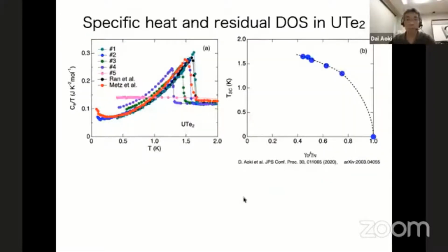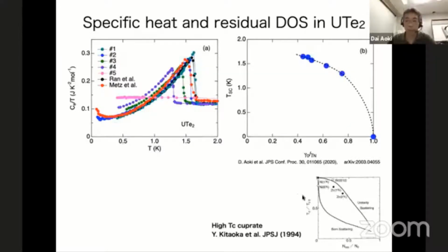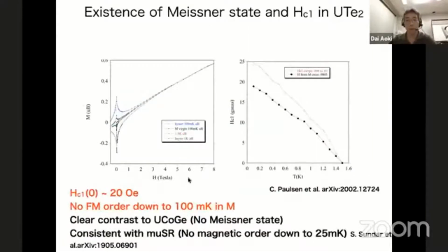Of course, this residual density of states is related to the sample quality. So we measured different samples and plotted like this. This relation was already known in the high-Tc cuprates a long time ago, but we don't know yet, so we have no conclusion so far at this point. Similar results are also known from Andrew Huxley's group. And in Grenoble, Cyril Paulsen measured the low temperature magnetization.